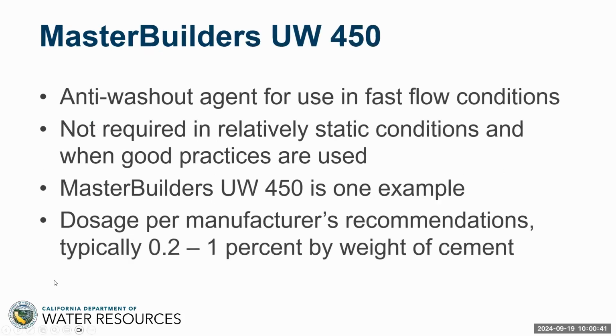Excellent material. Okay. Now then, Master Builders, one of the leading concrete and grout additive and admixture suppliers all over the world. They have a material called UW450. Other suppliers have similar materials. And this is an anti-washout agent, hence UW, anti-washout underwater. And it's used in fast flow conditions because, as most of you will know, if you try and put a normal cement grout in fast flow conditions, it will get extruded, it will get dissolved before it has time to fully hydrate. Again, check with the manufacturer, typically 0.2 to 1% by weight of cement.